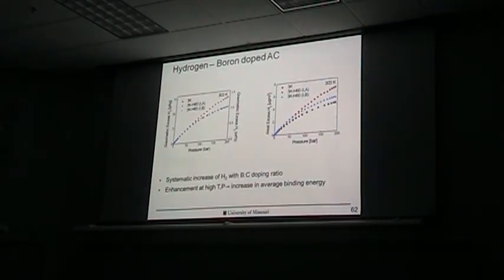And here you see, this is the undoped activated carbon. This is the doped one with boron doping. And you see at higher pressure, it gives you an advantage compared to the non-doped one. Because it's at higher pressure, we have an advantage. We think that the average binding energy increases. So the binding energy of the whole surface increases, and not like a single dot.